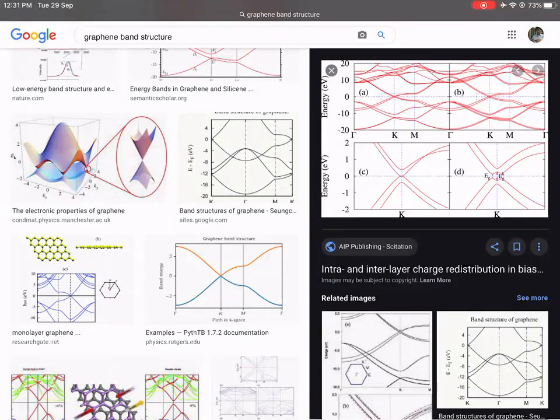So this is how typical band structures are drawn, and this is the only way you can draw band structures of 3D solids. If you look at the bottom line, for example, the energy is equal to minus 20 eV at gamma equal to 0. If we call that my first band, then as you change k from gamma towards K, you see how the band energy changes. So that is epsilon 1 as a function of k, and so on. That is how typical band structures look.